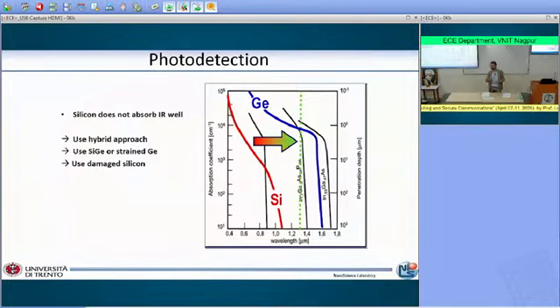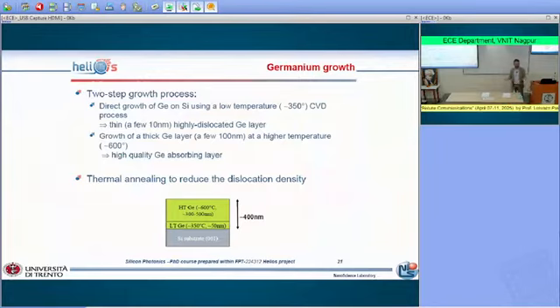Exactly. Strain. They do have a different lattice parameter. Therefore, you put your germanium on top of silicon and it gets strained. And so the stress at the interface is released by making defects, dislocation defects. So you can put germanium, but you get very poor germanium on top of silicon, and you do not get any good photodiode. Therefore, people have developed a technology, because nowadays you can have germanium photodiodes on silicon, by which they deposit a first layer of low temperature germanium that is essentially used to localize the dislocations at this interface. And then on top of that they put a very good quality germanium. In this way, they are able to put germanium on top of silicon.